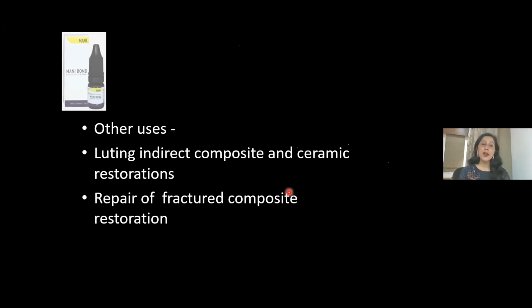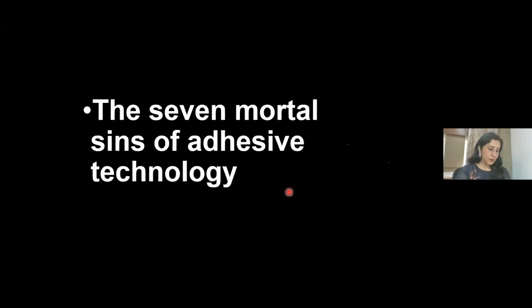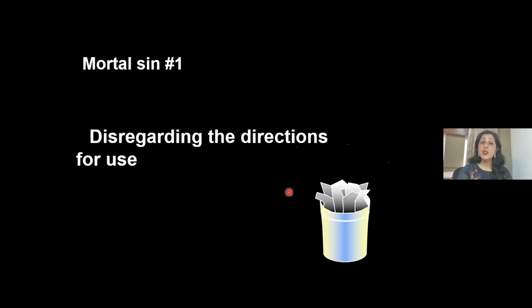The other uses where Monobond can be used are in luting, indirect composite and ceramic restorations, and repair of fractured composite restorations. If your composite restorations are fractured, then this does an excellent repair. And since I'm using it for a long time now, I can tell you that it has really good results.